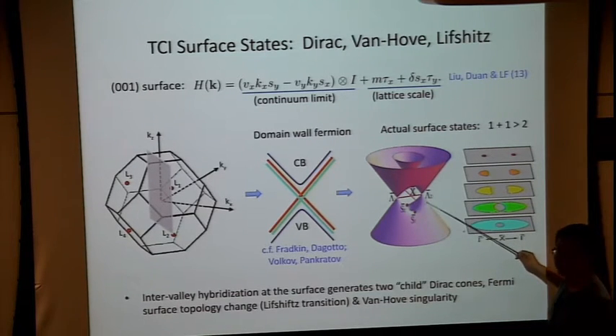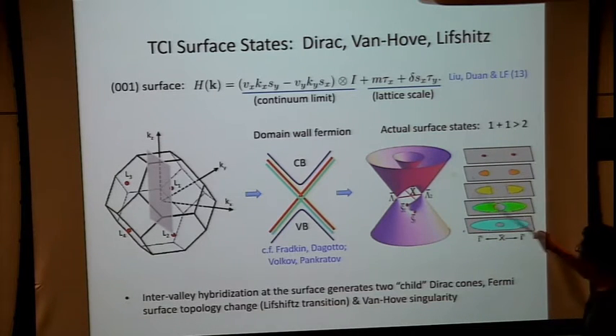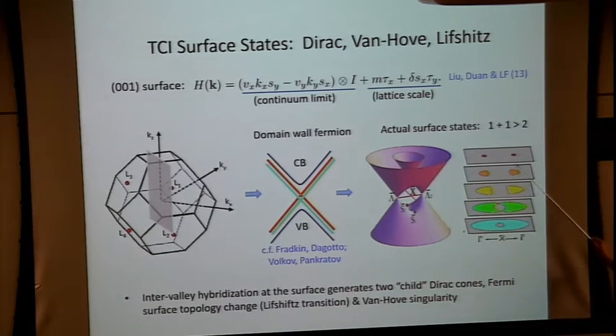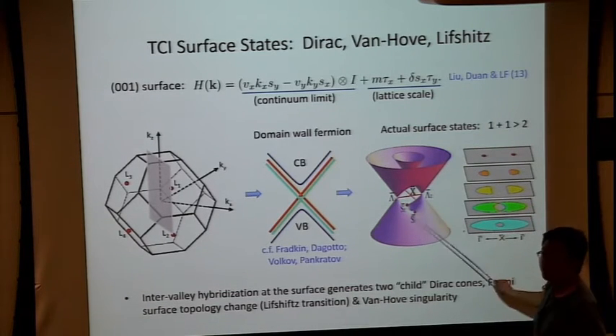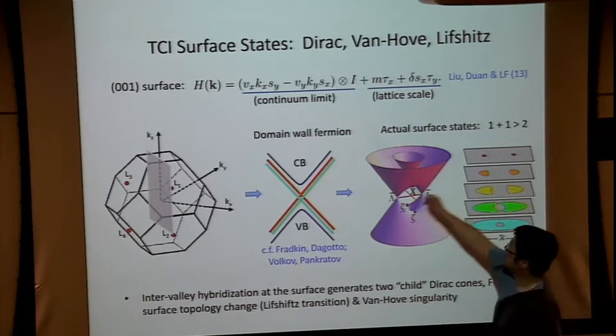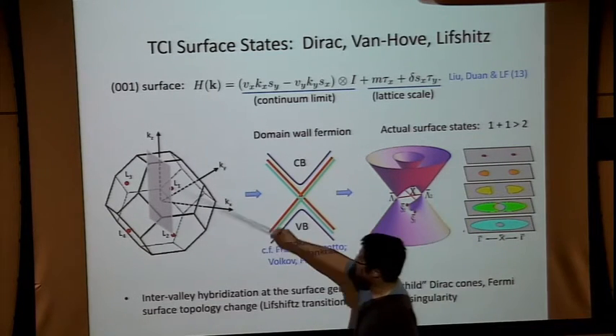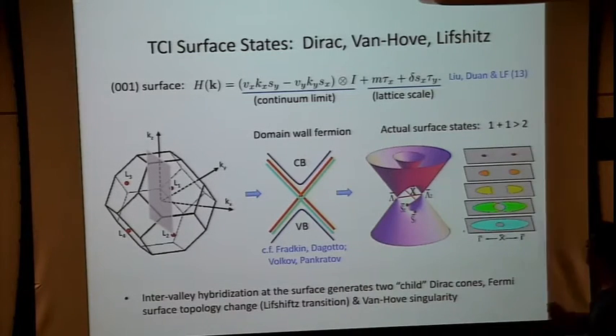it has a lot of features. At low energy, we have the Dirac cones, but at high energy, the Fermi surface of the Dirac cone is severely distorted, and then above a critical energy, the two Fermi pockets merge with each other. This is a Lifshitz transition, and after that merging, there's one big electron pocket and a small hole pocket concentric around the X point. Okay, so basically, there's a hierarchy of energy scales in this problem, and that is due to this particular fact that the two L points project onto each other. Okay? And again, mirror symmetry plays a crucial role.